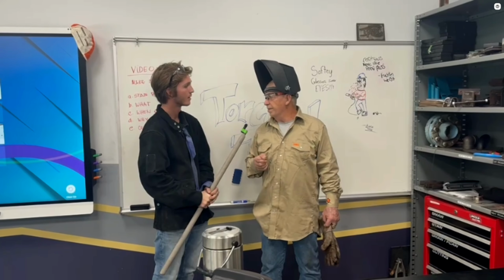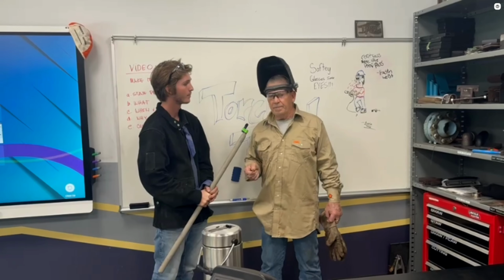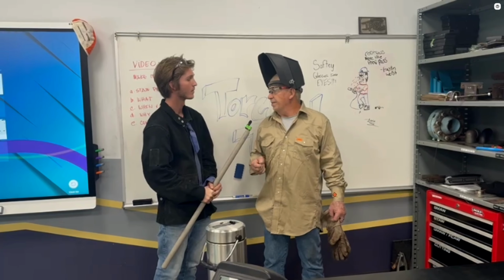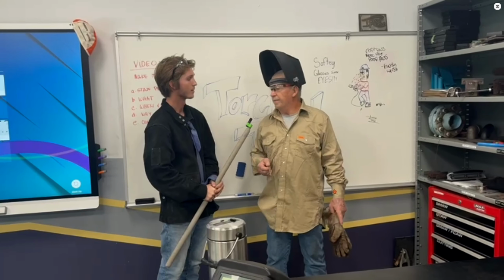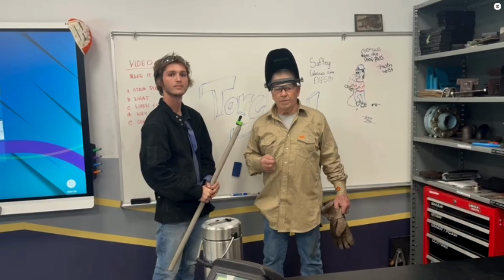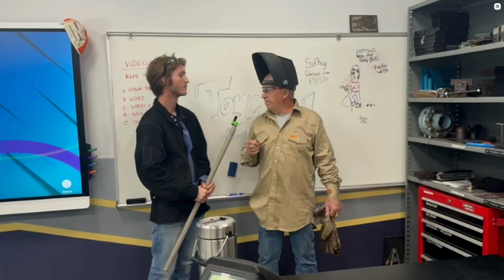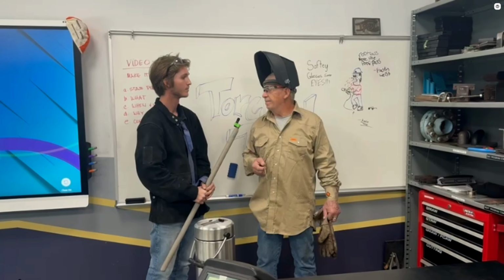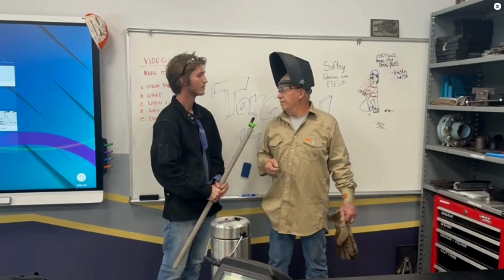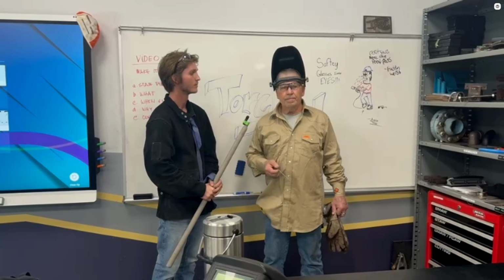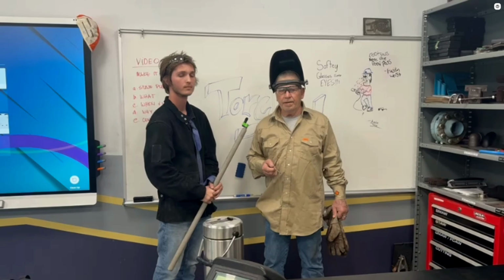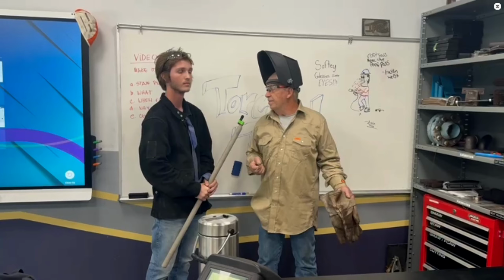Next, we've got fast fill electrodes such as 7024. They're basically the opposite of the fast freeze because the puddle stays fluid much longer and deposits a lot of metal quickly. They're ideal for flat and horizontal welds, mostly on thicker plates. They don't really handle out of position welding well because the puddle is so fluid.